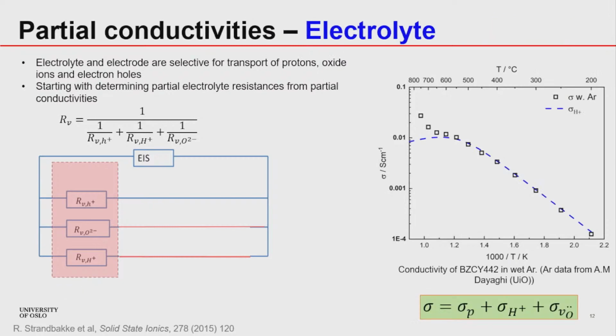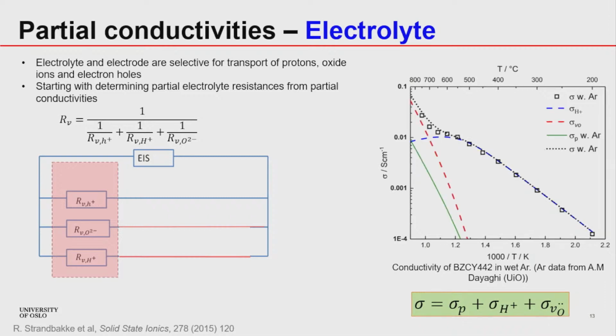And then we can model the data and we can get the proton conductivity and the oxide ion conductivity, and the very little p-type conductivity. So all the dashed lines are the model data, and the open symbols are the experimental data.